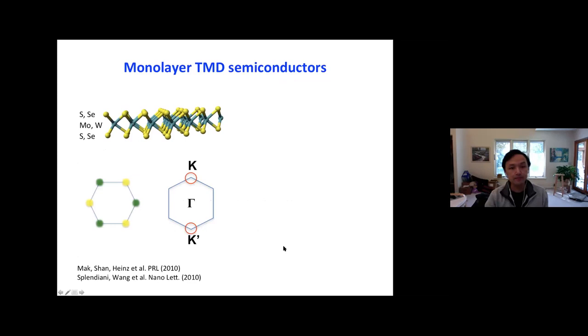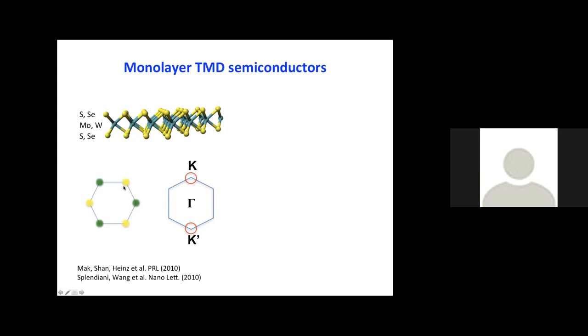The semiconductor that we will be using is a monolayer transition metal dichalcogenide semiconductor, TMD. Its structure is like this. A monolayer of this material consists of three layers of atoms, with the middle layer of transition metal atoms sandwiched between two layers of chalcogen atoms. If you look top down, it looks like a honeycomb structure, just like graphene, except that the A and B sites are now occupied by different atoms.